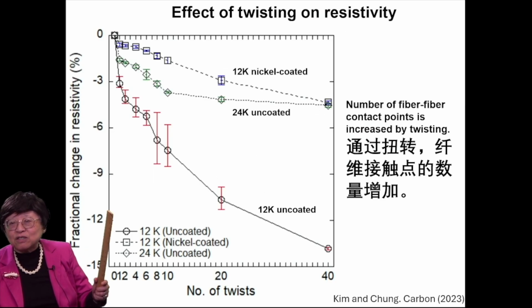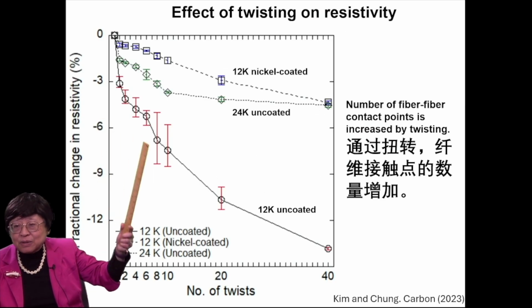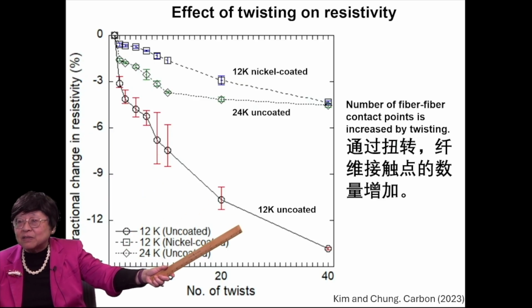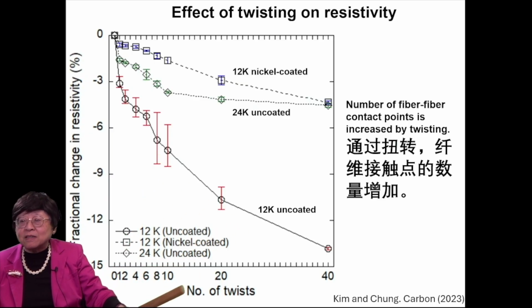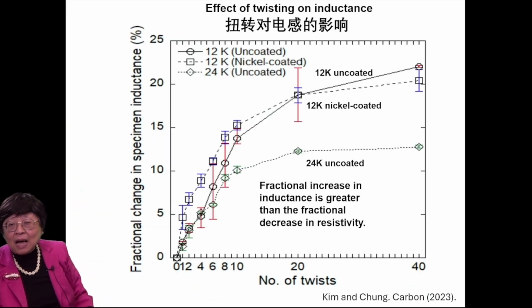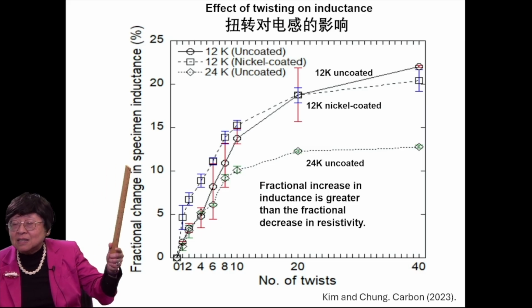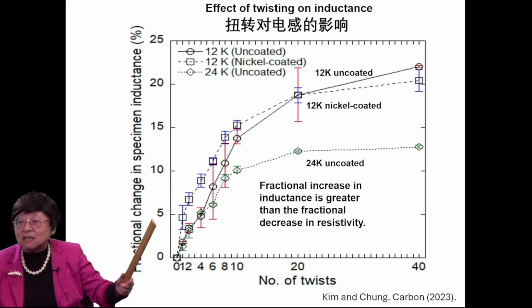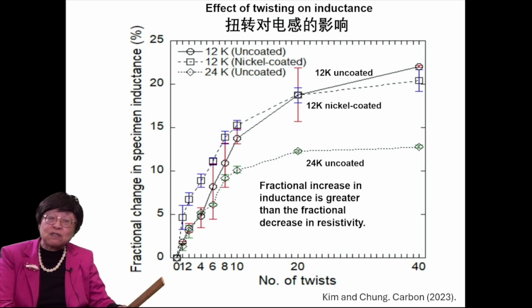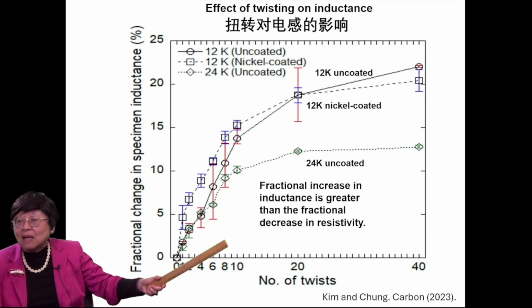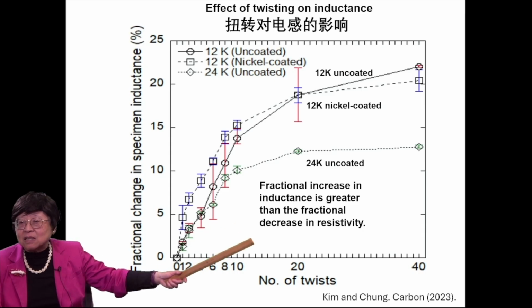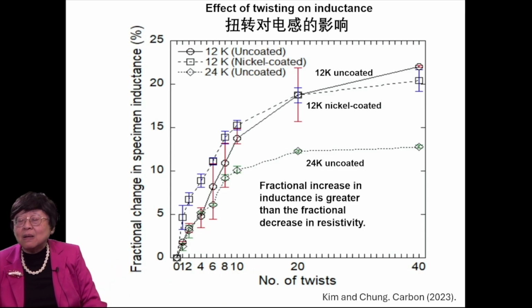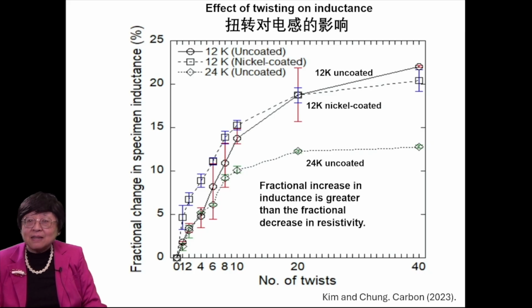And this shows the fractional change in resistivity, and it decreases as you have more twists because the number of fiber contact points is increased by twisting, so the resistivity decreases. However, the inductance increases, and the fractional increase in the inductance is high compared to the fractional decrease in the resistivity. And so the inductance increases with the number of twists of the tow, and that provides the inductance-based self-sensing of the twist level of carbon fiber tow.